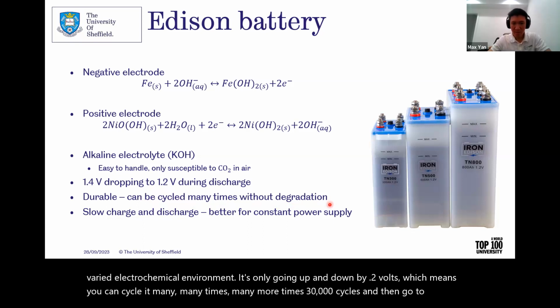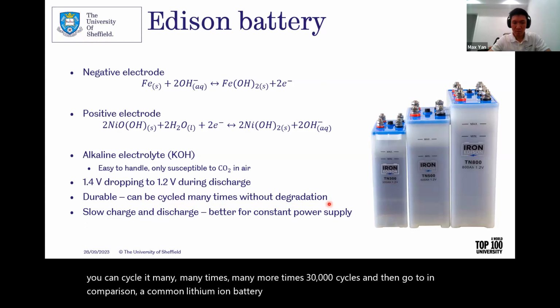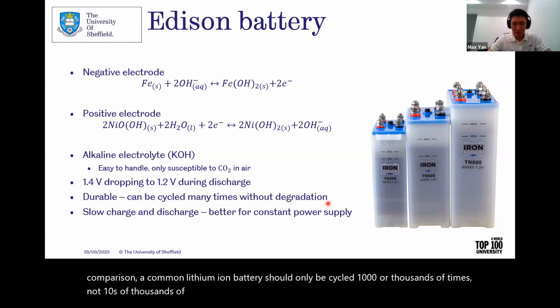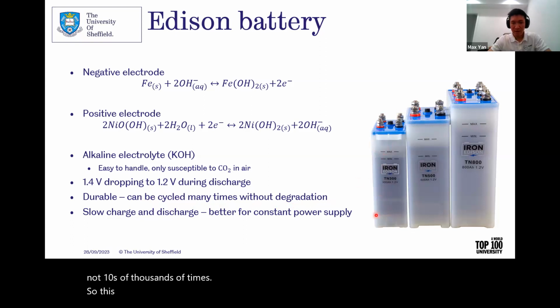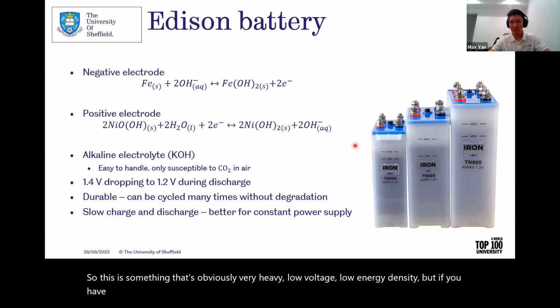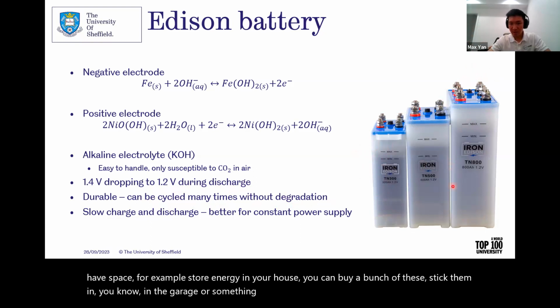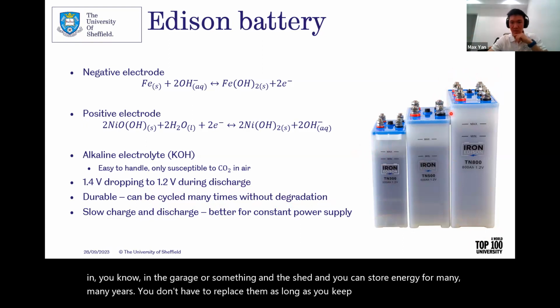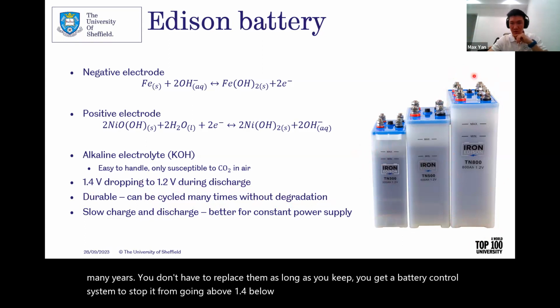In comparison, a common lithium-ion battery should only be cycled 1,000 or thousands of times, not tens of thousands of times. So this is something that's obviously very heavy, low voltage, low energy density. But if you have space, for example, to store energy in your house, you can buy a bunch of these, stick them in the garage or the shed, and you can store energy for many, many years. You don't have to replace them as long as you get a battery control system to stop it from going above 1.4 or below 1.2. And you can store a lot of energy for a long, long time.